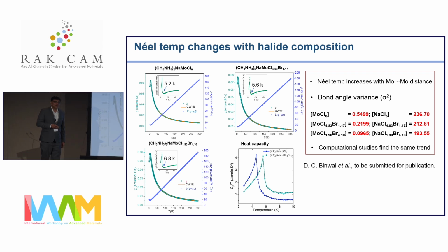Why? Because it's counterintuitive compared to what is known in the literature. Because with bromide, the molybdenum distance in the chain increases. That's supposed to reduce the magnetic correlation temperature. The magnetic exchange should become weaker, but here we see it is becoming stronger, which is further verified by heat capacity measurement, where the mixed halide is showing the anomaly in heat capacity at higher temperature.